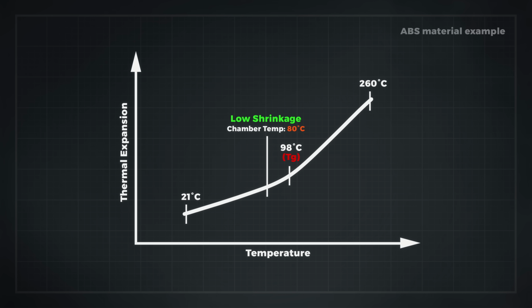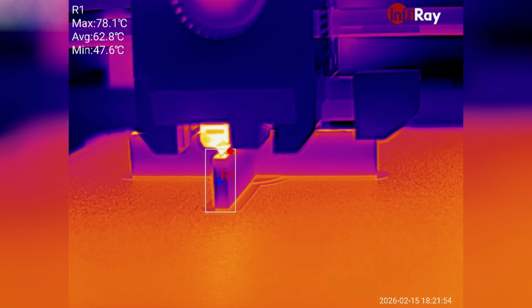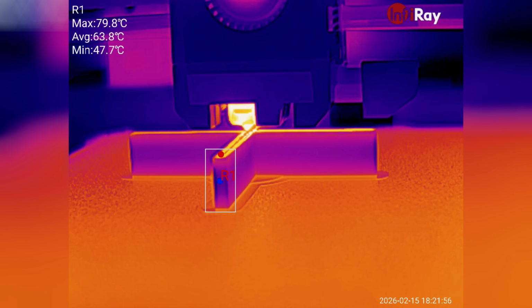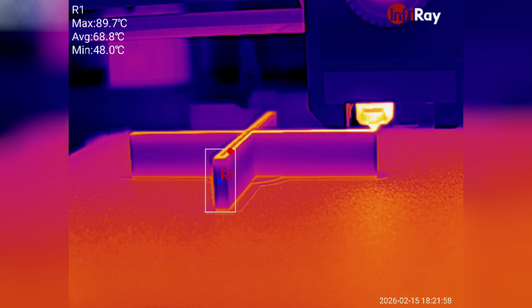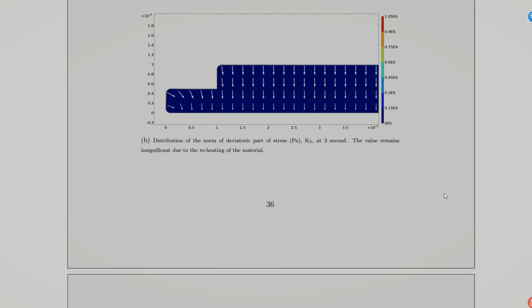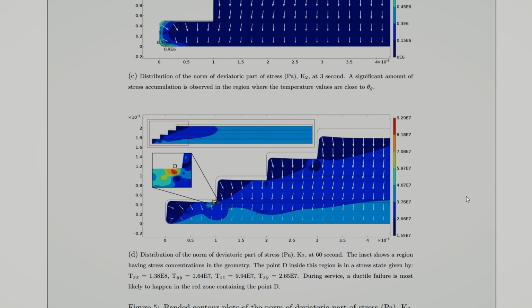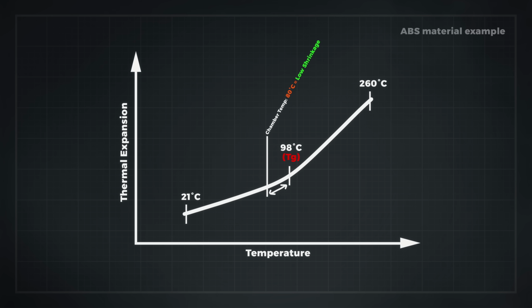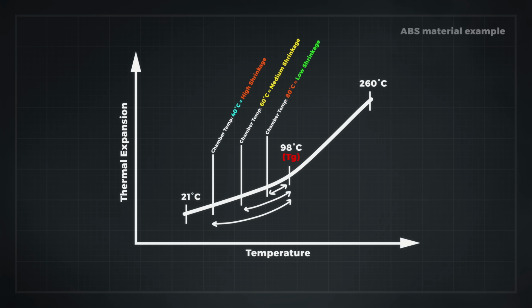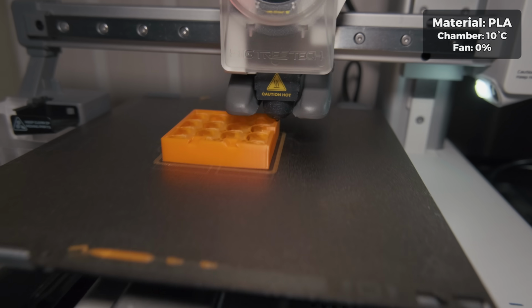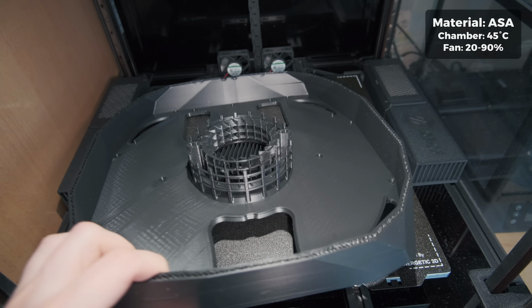The further this temperature is from the material's glass transition temperature, the more the plastic will shrink. Because the print is a single object but does not cool evenly, instead cooling in sections, each additional layer increasingly pulls on the previous one due to shrinking forces. The larger the temperature difference between the glass transition temperature and the chamber temperature, the stronger these forces become. This leads to accumulating stress until either bed adhesion fails and the print warps, or with materials like ASA, delamination can